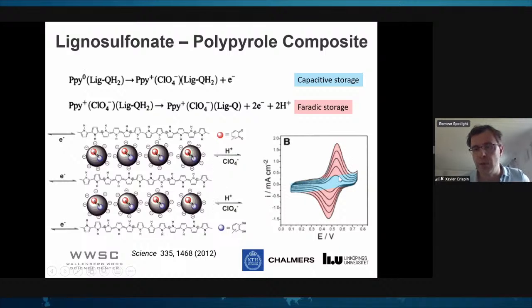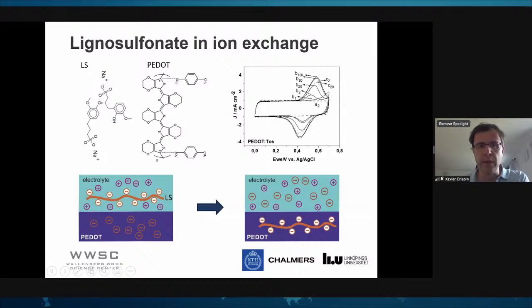And this is basically the red peaks that you have. It's a Faradic peak. So you see that you have a capacitive behavior due to the conducting polymer, but you also have a Faradic behavior due to the quinone that is in your lignin. And this is basically enabling a higher charge storage. So that is another example that I will skip.